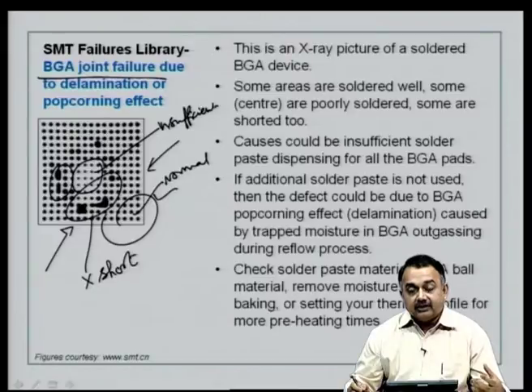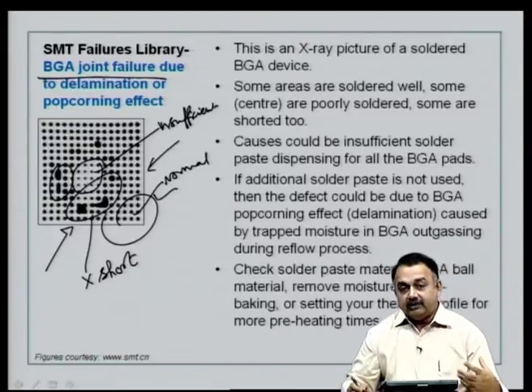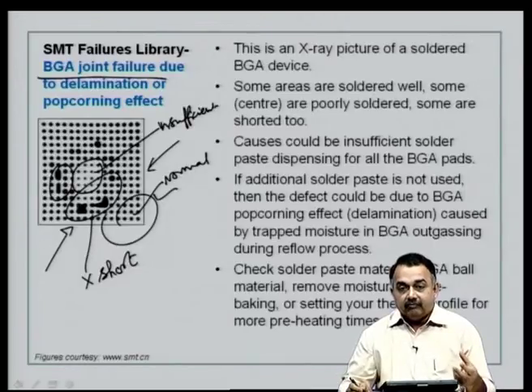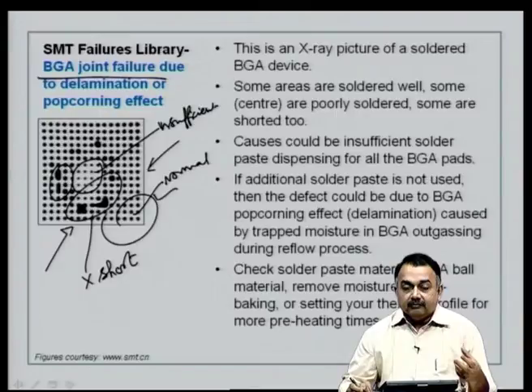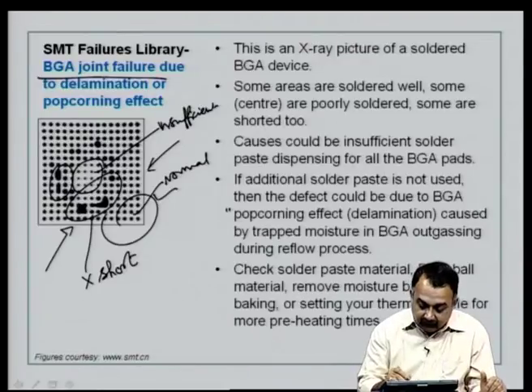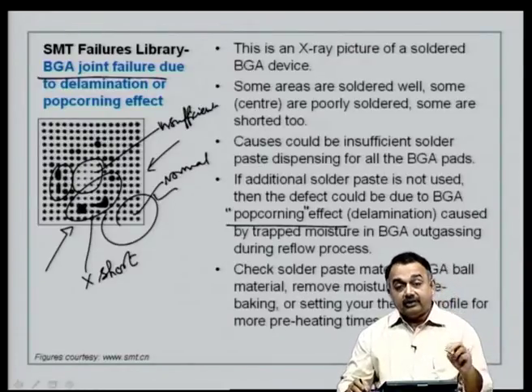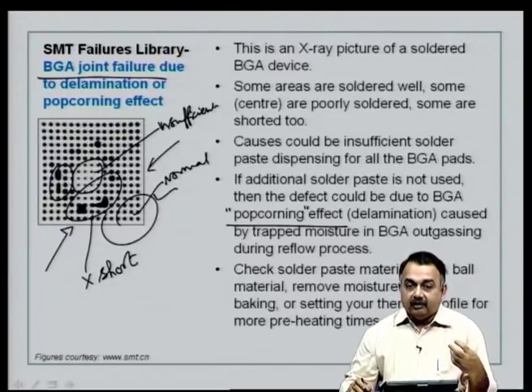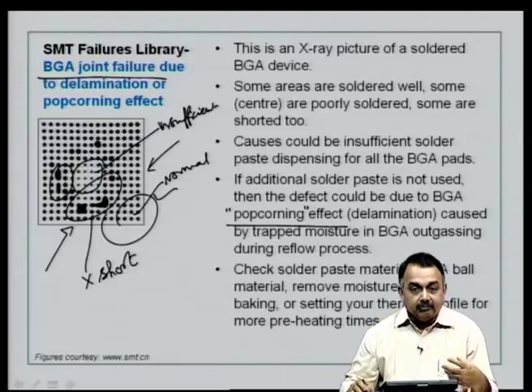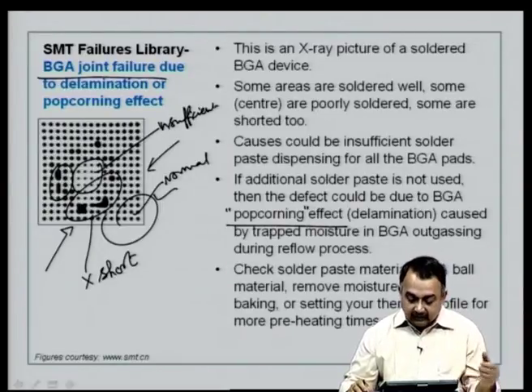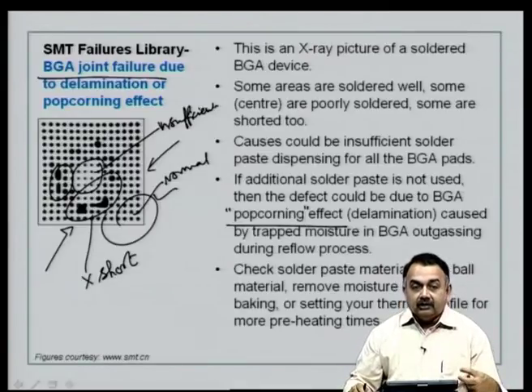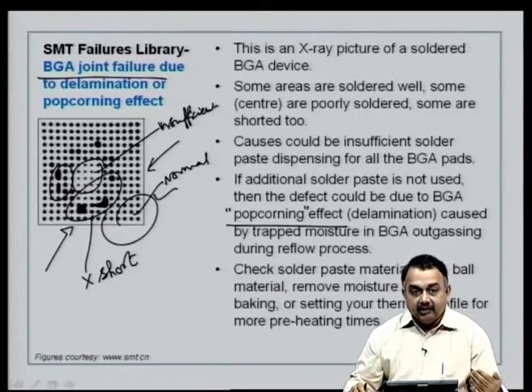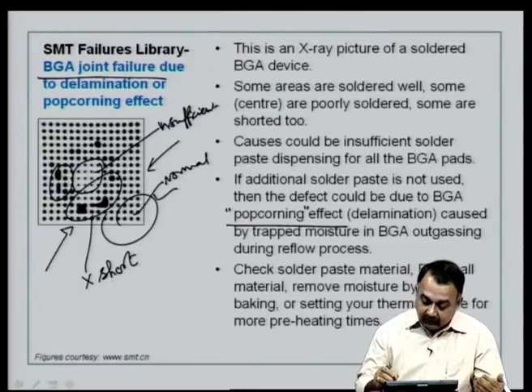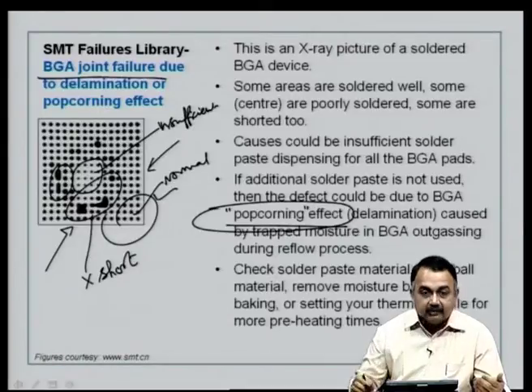If you have not used additional solder paste for attaching a BGA, that means you are using the BGA solder ball itself to reflow and then form an interconnect to the board, then this could be due to a delamination or popcorning effect, as you call it, very common in BGAs. Again, this is due to the plastic body of the BGA absorbing moisture. Okay. Epoxy, as you know, is well known for its moisture absorption, and before you are doing the process, you have to do a pre-bake. If you have not done a pre-bake, then you will see this kind of a popcorning effect.